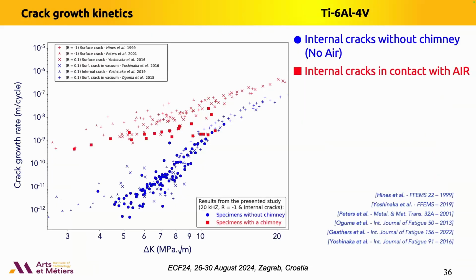So you can find that on the Paris diagram. This is the red square. Our data are the red squares, the specimen with the chimney, compared to the blue round points, the same specimen without air. So you can see that when delta K is small, there is a very big difference in the crack growth rate. And our data are compared with the red crosses coming from literature data. Again, we can see that our data are in agreement with the literature for specimens with a surface crack. All the crosses correspond to literature data with a surface crack in air. So this diagram shows that an internal crack with air propagates at the same speed for an equivalent delta K as a surface crack in air.